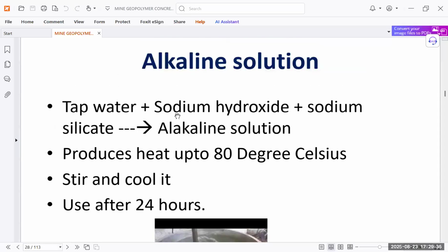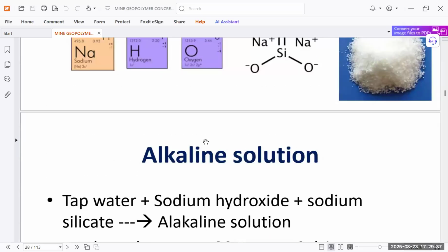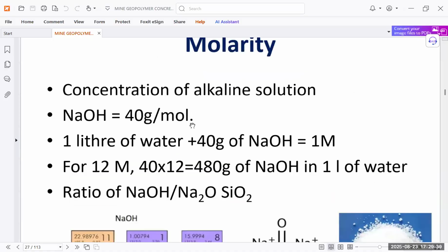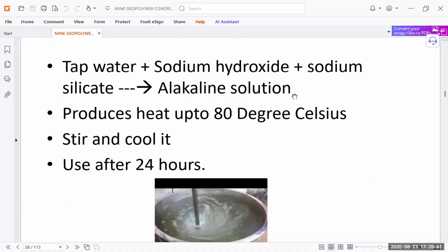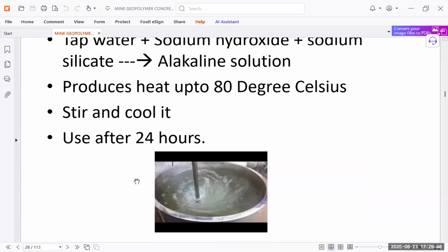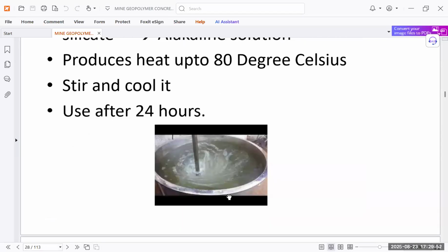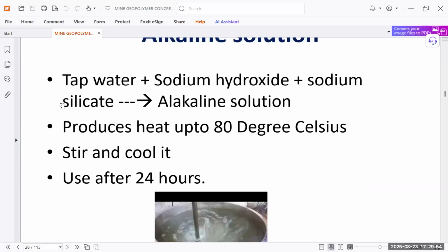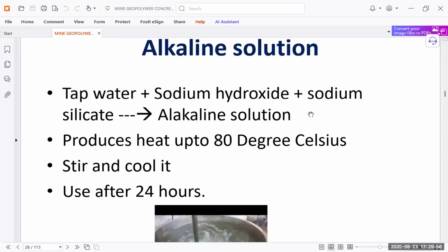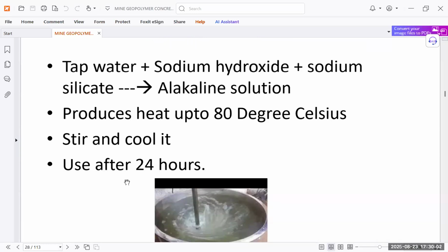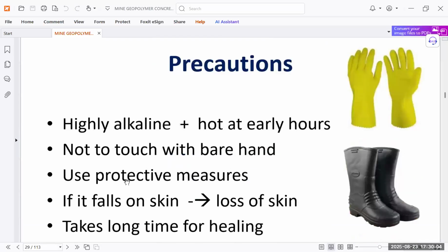Tap water will use the sodium hydroxide plus sodium silicate that has been formed here. And then we will make this alkaline solution, and then we will heat it up to 80 degrees Celsius. Then we will stir it and cool it, and we will use it after 24 hours. This is the way this alkaline solution is made by using tap water plus sodium hydroxide plus sodium silicate. We make the alkaline solution, then heat it up to 80 degrees Celsius, then stir it like this, cool it, and use it after 24 hours.